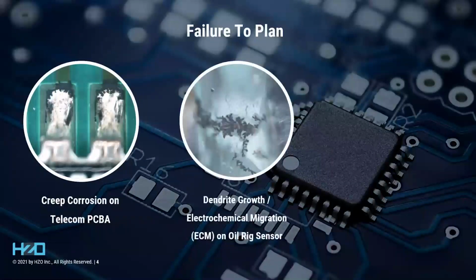Creep corrosion can lead to dendrites, and that's the migration of ions between two things, leading it to grow a chemical structure between the two. These dendrites grow across the surface of the components or on the surface of the PCBA, leading to electrical shorts, which do result in failure of the PCBA and subsequent systems and product.